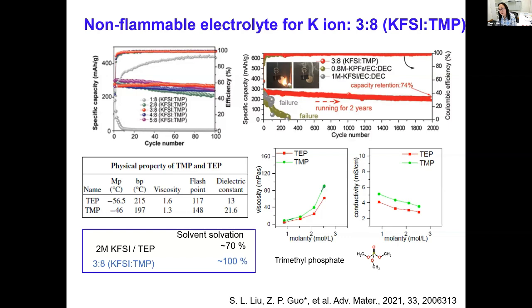So keeping this in mind, we found TMP, which has a higher dielectric constant, and so very likely gets into the solvation shells of the structure. And also this TMP has a lower viscosity and higher ionic conductivity. So it seems quite ideal to be used as a solvent for the development of non-flammable electrolyte. So then we dissolved KFSI in the TMP to form the electrolyte. The ratio 3:8 is equivalent to 2 M, similar to the previous work. And we found that by using TMP, we can achieve 100% solvation.